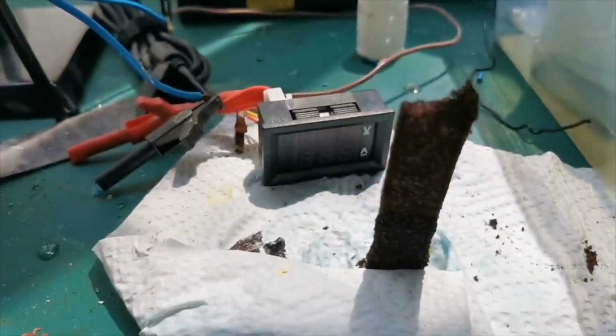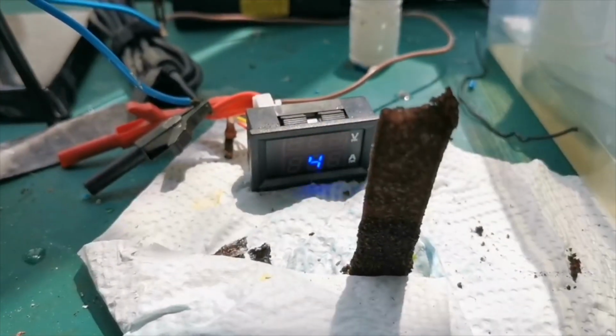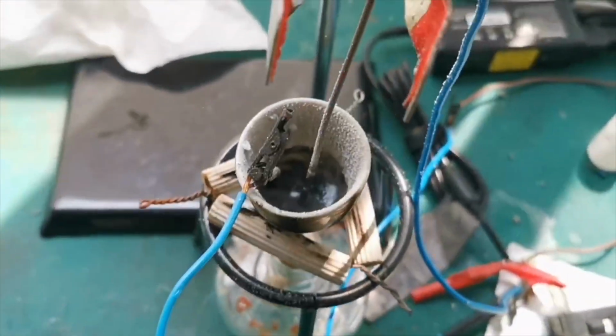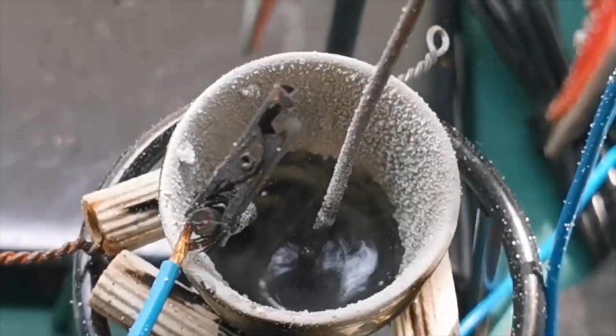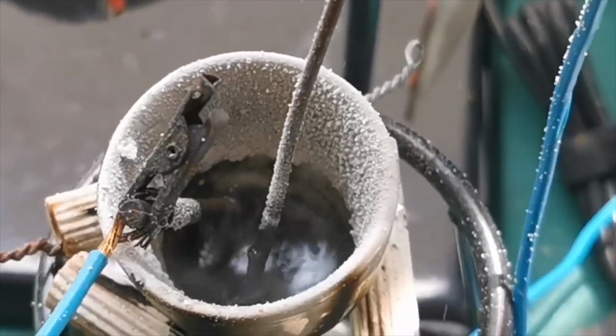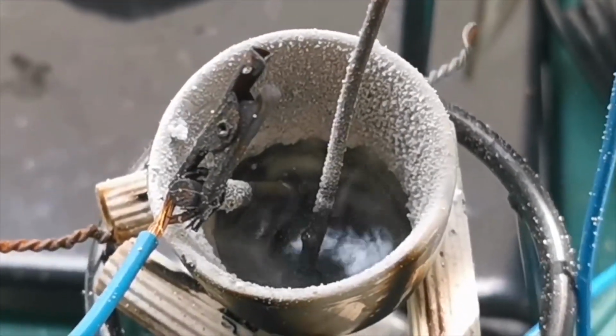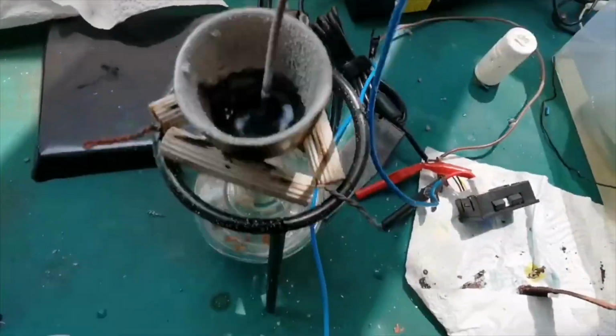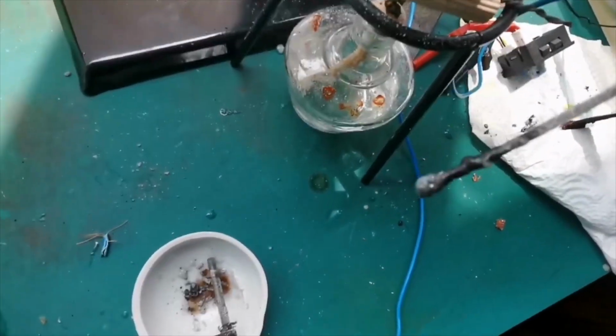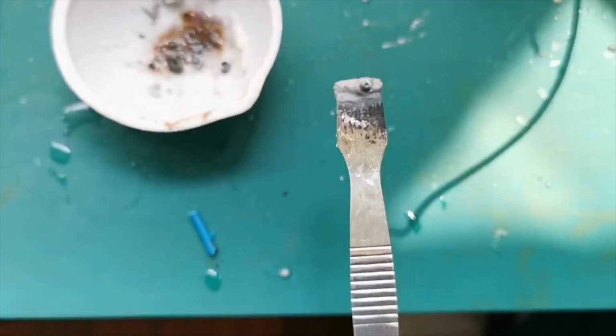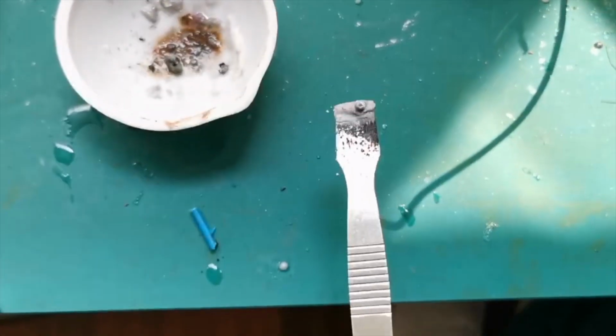I left the cell running for 10 minutes, and the current rose rapidly to 3.44 amps. The large current produced bubbles much more vigorously, and sprinkled salts everywhere. I took out both the electrodes and let them cool down. I then scraped the largest bead of lithium out of the cell, and here is what I've got.